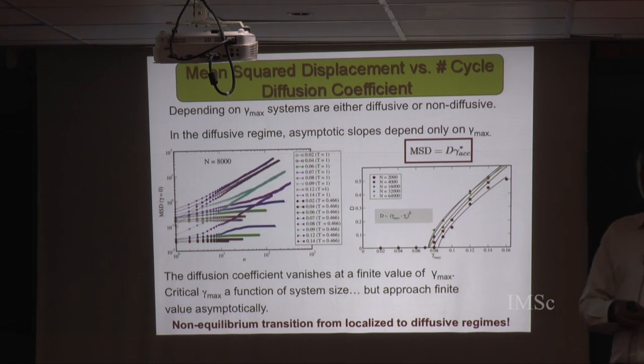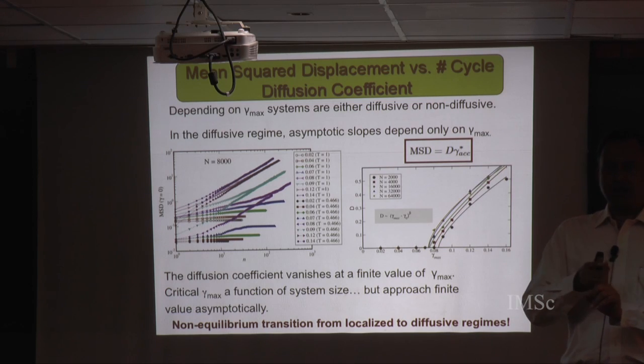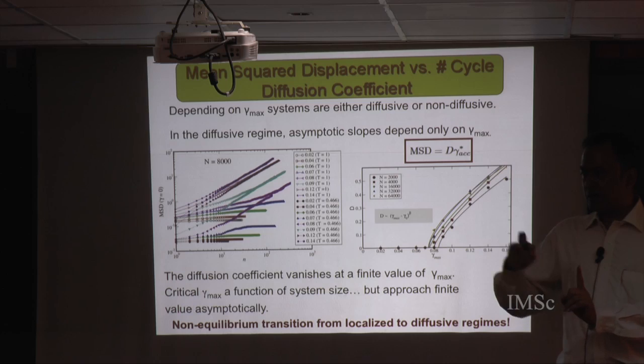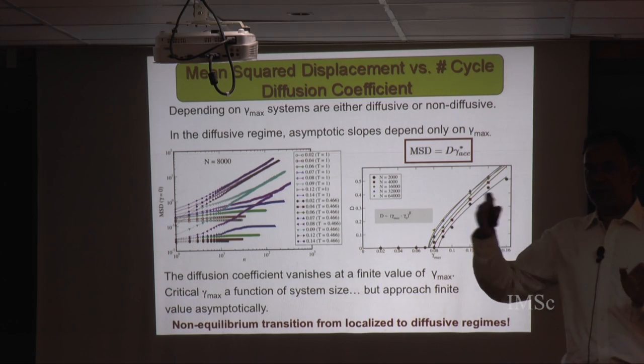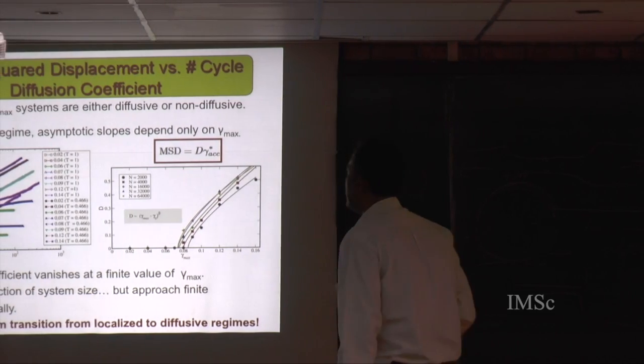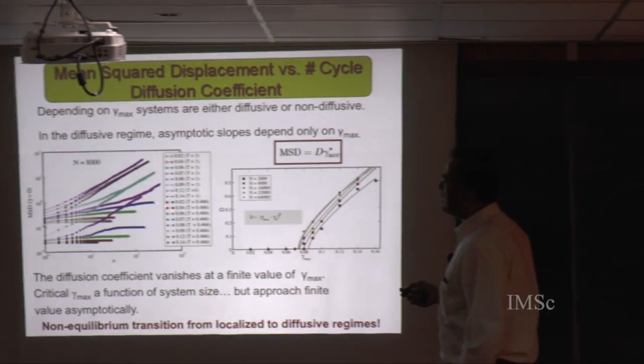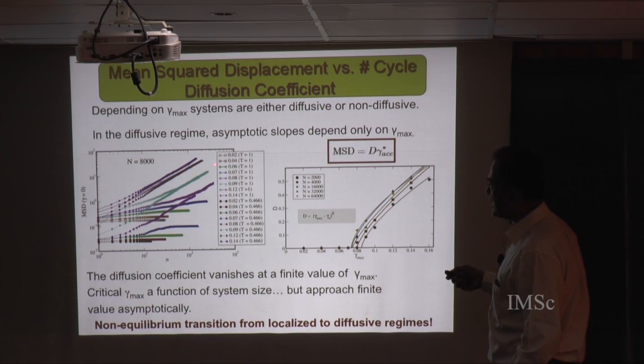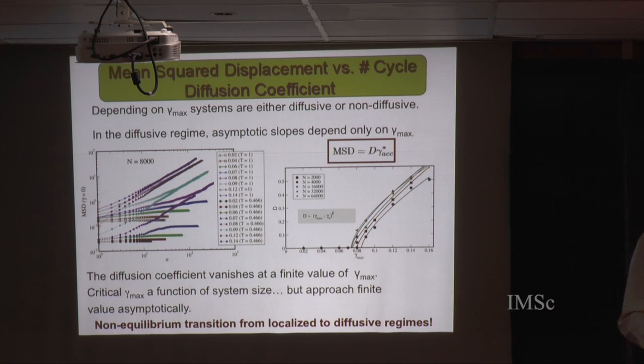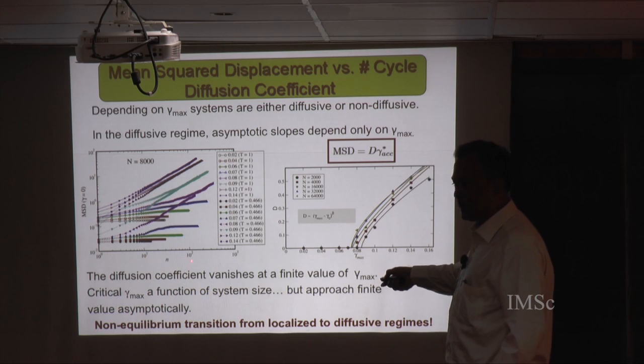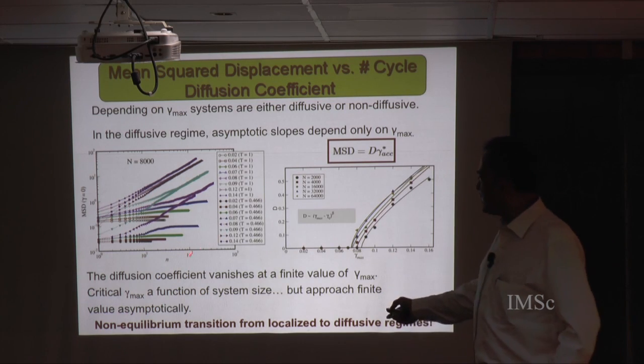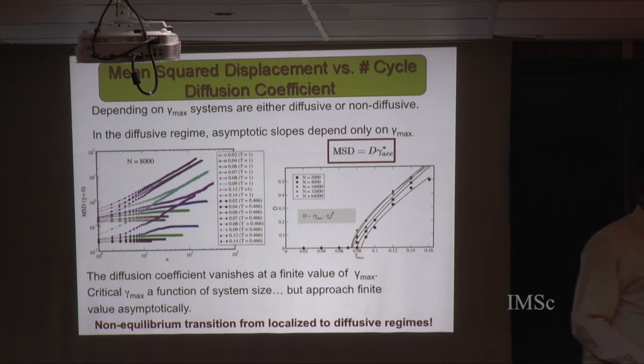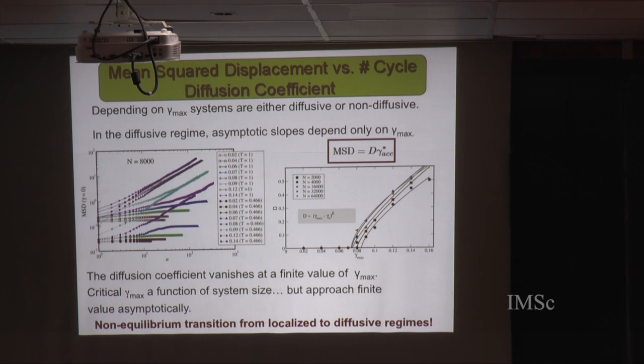When you look at the positions of atoms at the end of each cycle, stroboscopically - we look at mean square displacements by looking at configurations at the end of each cycle - whereas at large amplitudes, most clear at the largest amplitudes we study, the mean square displacements become linear in the number of cycles for sufficiently large numbers of cycles. In other words, if I think of the number of cycles as a time variable, what I'm seeing is a transition from a non-diffusing to a diffusing state.